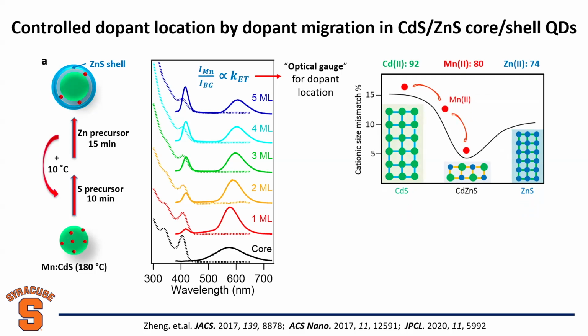The manganese is 80 picometers, Cd is 92 picometers, about a 13% size mismatch. And if you grow zinc sulfide here, zinc is 74 picometers, too small. But when you grow the shell onto the core, you're not going to have a sharp interface. You can have an alloy interface there. So basically, the alloy zinc can provide an intermediate lattice site for the dopant.